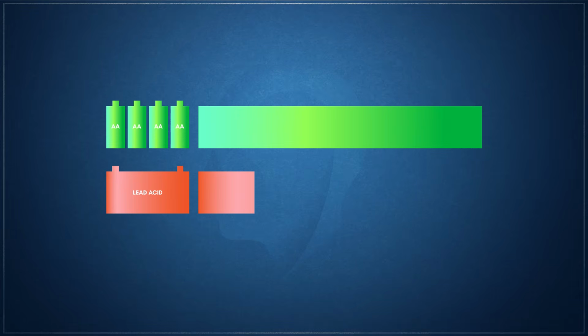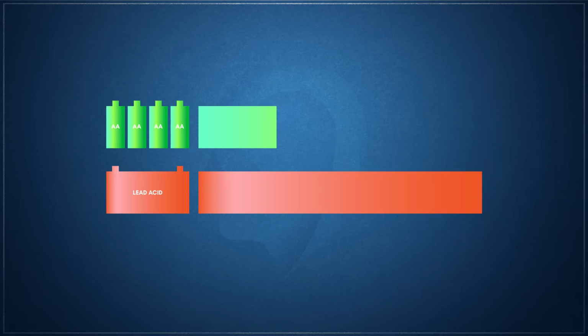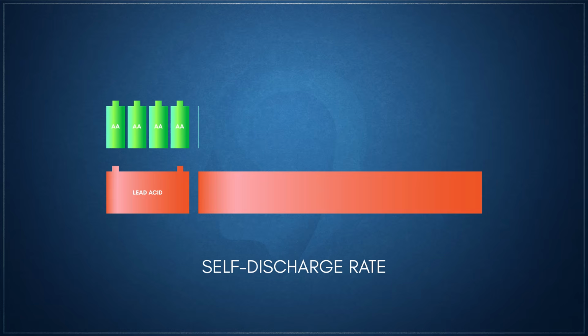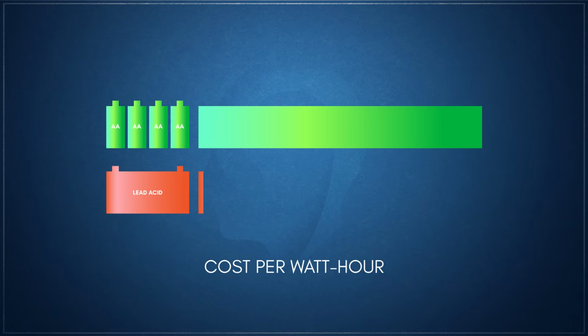A typical modern AA alkaline primary battery, for example, when compared to a lead-acid cell, has almost 4.5 times the specific energy, 5.5 times the energy density, but only 1/3 the specific power. They also have incredibly low self-discharge rates, losing only about 0.17% per month, as opposed to the 3 to 20% for a lead-acid cell. Where a lead-acid battery stands out compared to other more superior chemistries is in cost. A lead-acid battery can store almost 40 times more energy per dollar than the more energy-dense AA battery.